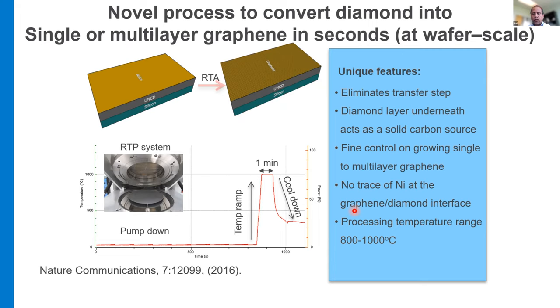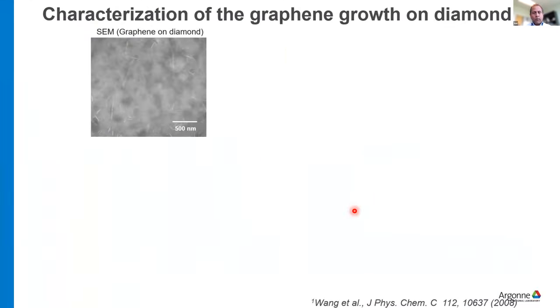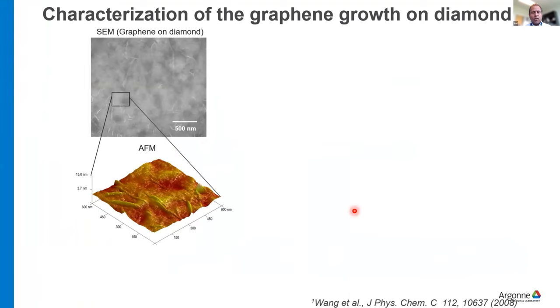And within a few seconds or within a minute, you can convert the whole 4-inch wafer into the single or multi-layer graphene. So we already have several patents on this process, and this was published some time back. But let me walk you through the characterization of the graphene.